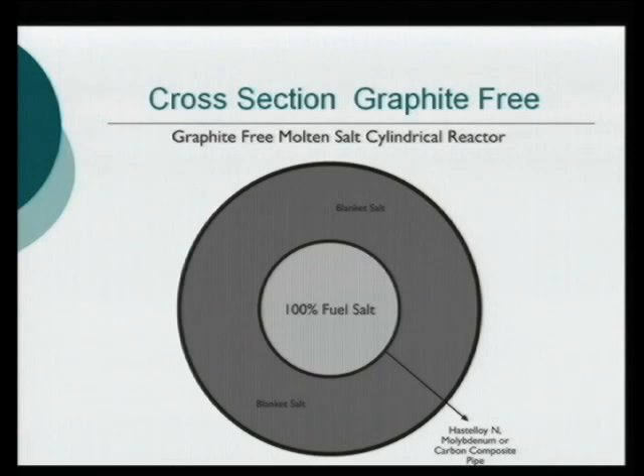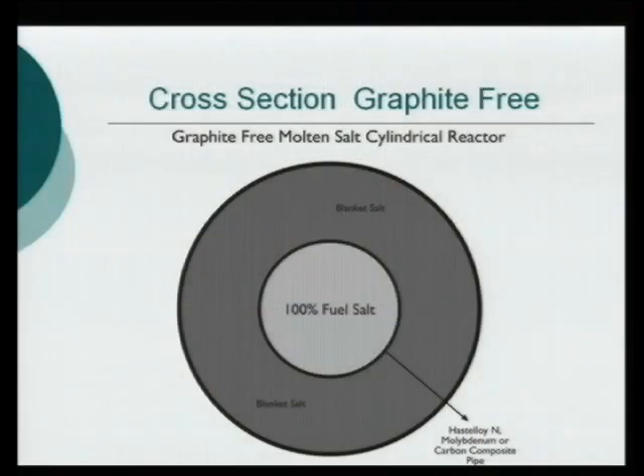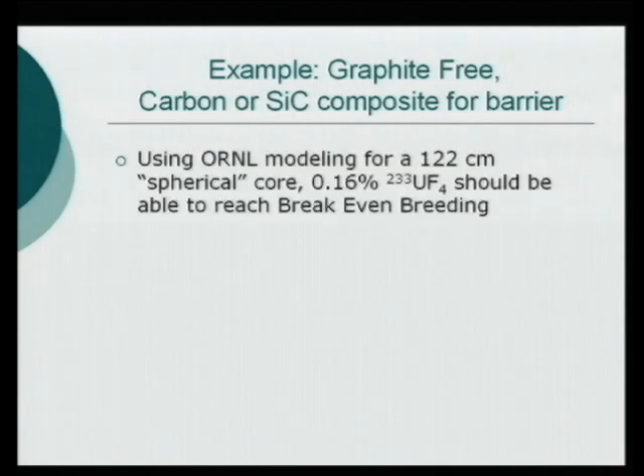So showing a cross-section of graphite-free, meaning we don't have any solid moderator. It's basically just a pipe within a pipe, and sometimes people have used the term tube within shell, which is a heat exchanger term. Now we do need a barrier between the two, like Oak Ridge often had. That could be Hastelloy perhaps. Molybdenum is a great material neutronically and for radiation damage, but really hard to work with. Or maybe just simple carbon composites or silicon carbide, etc. A lot of choices here.